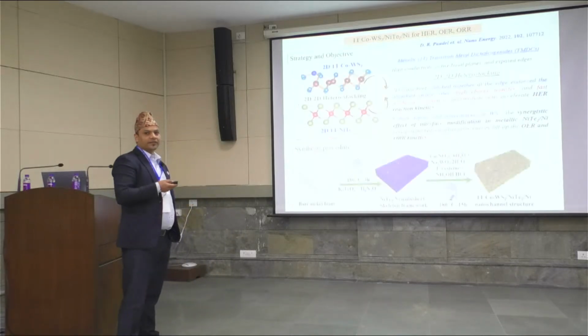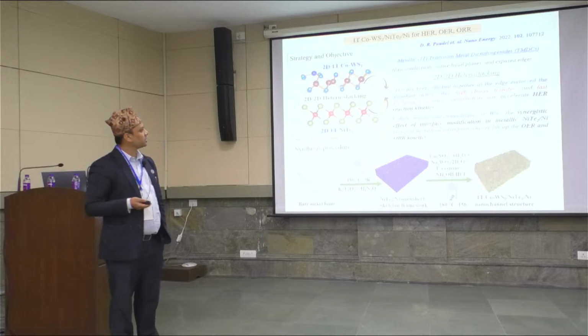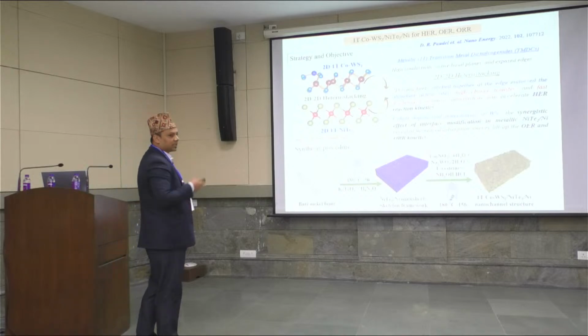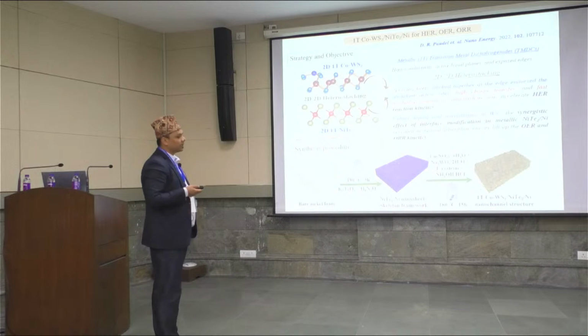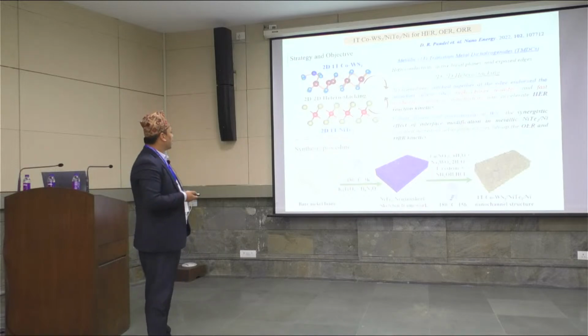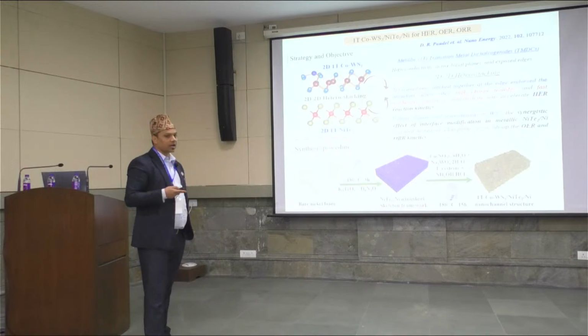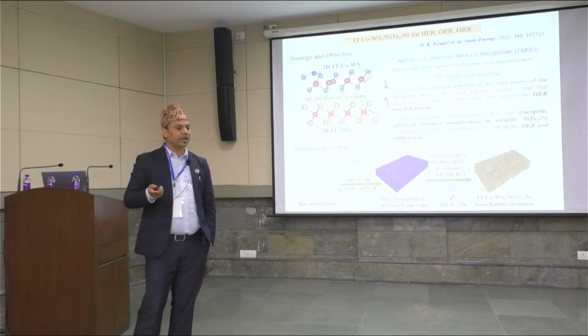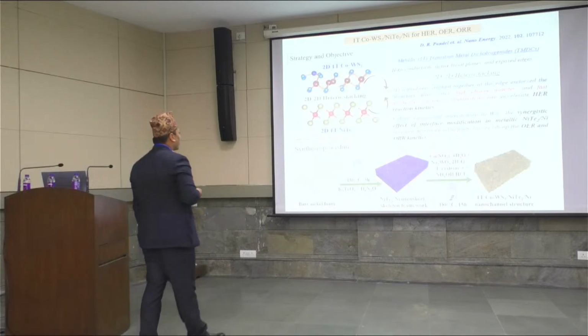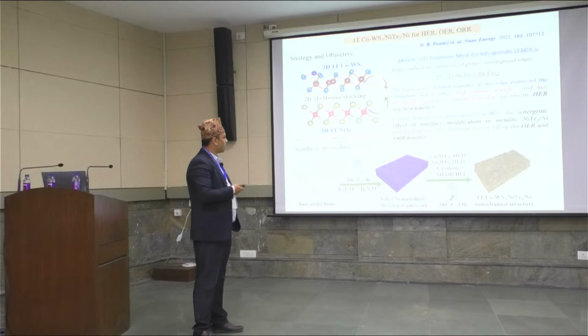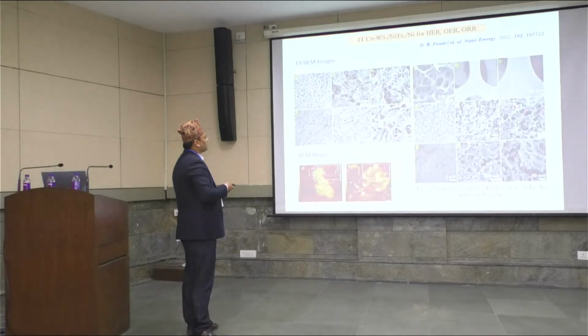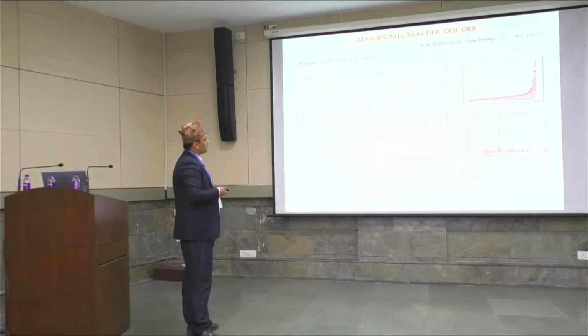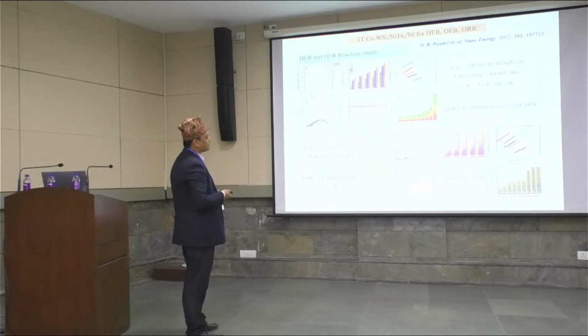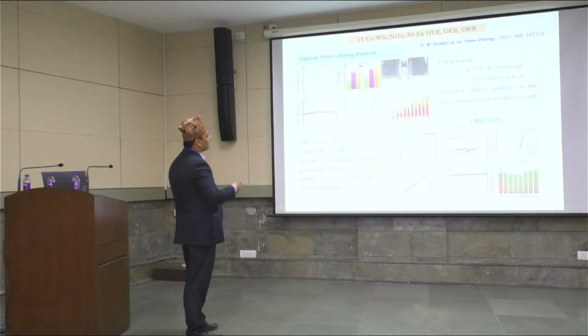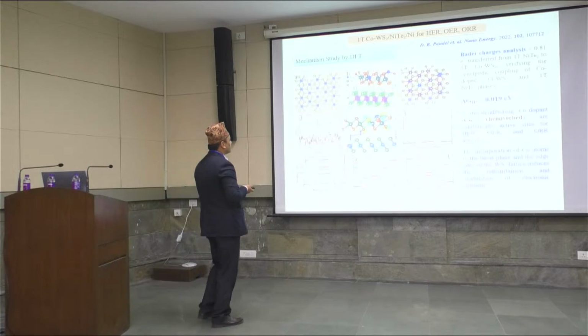I just want to skip this because this work is also published in Nano Energy in the 2022 issue. And here we make the heterostructure of 1T CoWS2 with nickel telluride as a framework. And here we see the heterostacking of 2D material, and it shows a very good electrocatalytic property. We checked for HER, OER, and ORR applications. And these are the FESEM images and other characterization tools. And this is the HER and OER reaction where the cell potential is very low, around 1.53. And a mechanistic study by DFT.